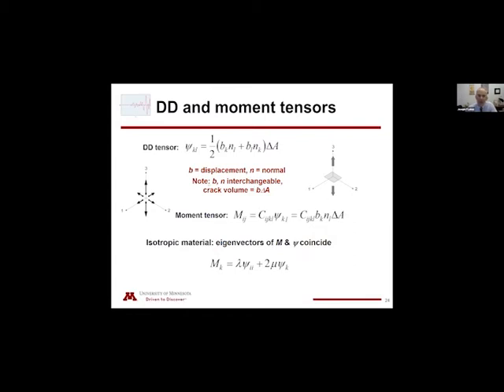Now, another way of approaching this is to look at, instead of the moment tensor, what is sometimes referred to as a displacement discontinuity tensor or a crack tensor. And that's this quantity psi, where B is the displacement vector and N is the normal vector. And immediately you see that we could interchange B and N, and psi does not change. So this is a limitation of the analysis. There is a simple relationship between the moment and the displacement discontinuity, and that's given by the elasticity of the material. So we could write the moment tensor in terms of B, N, and delta A by knowing the elasticity of the material.